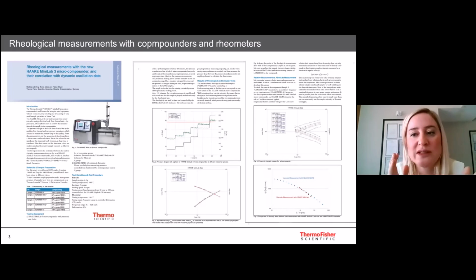So we take again the measurements during the compounding, and you see that the measurements we take from slits, what we call slit capillary, are relative measurements, but whenever we compare them with the absolute measurements taken from the rheometers, they are matching, they are identical and correlating to each other. But as I said, if you want to broaden the range, we still have rheometers for dynamic oscillation data.